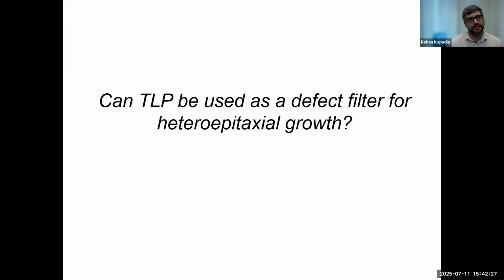I didn't put a big set of slides in here describing the traditional state of the art for heteroepitaxy on silicon, but fundamentally, the approach that people use is to create some kind of buffer layer, and that buffer layer can be composed in different ways. The whole job of that buffer layer is to essentially take all of the defects that get formed when you create, say, a III-V silicon interface and somehow recombine them or bend them or prevent them from propagating all the way up. And then you grow a high quality layer at the top of that.